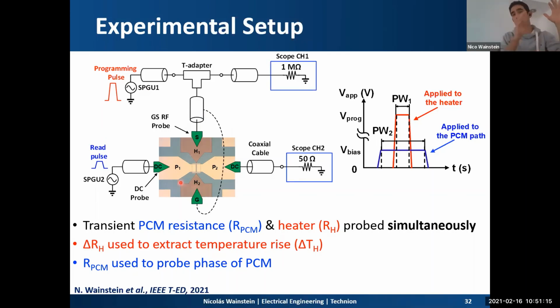With the COMSOL model and the compact model, we can determine the PCM temperature, calibrated using both the COMSOL simulations and the compact model. That gives us an indication of the temperature at the PCM. When probing the phase transition resistance, as you can see here, there is also another pulse simultaneous with the heating pulse, which allows us to check the current variation. We check the voltage at the scope divided by the 50 ohms of the scope, and we have the current on the phase change material path.